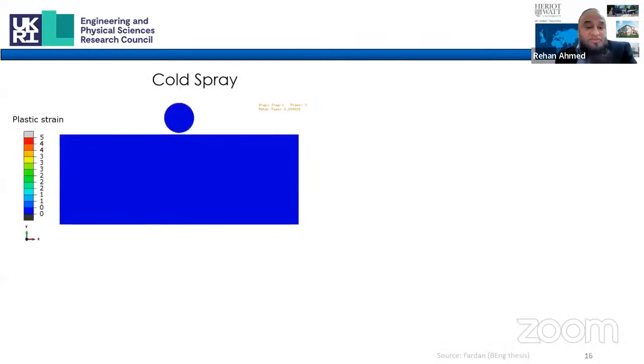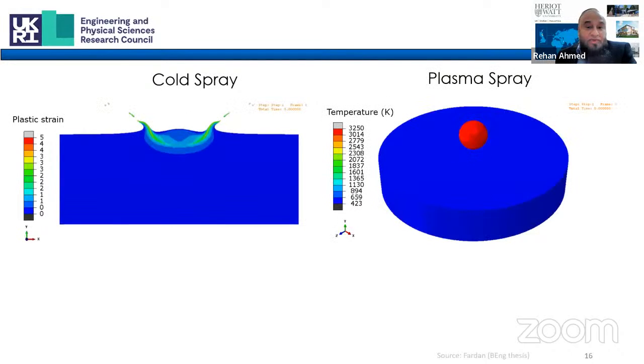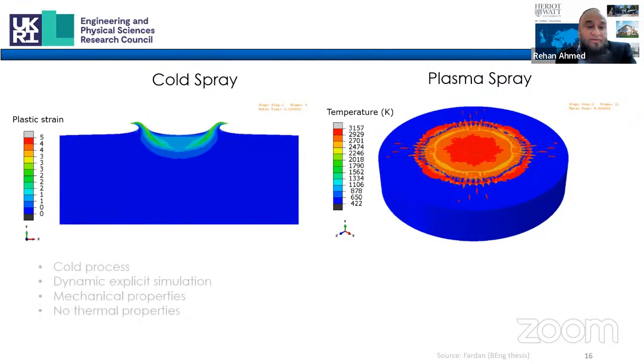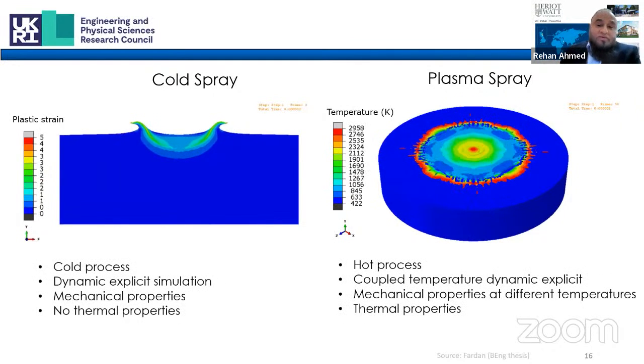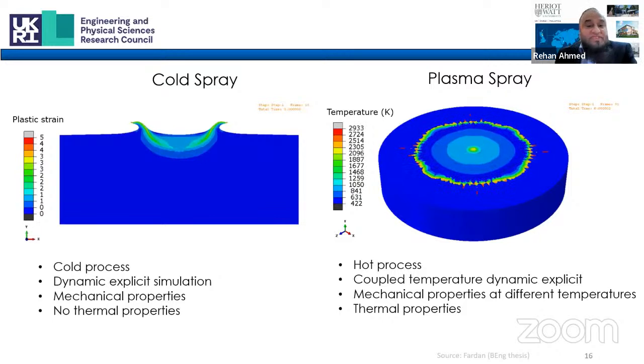And I'm just going to show 2 examples of simulations performed using the Eulerian method. On the left-hand side, cold spray is a cold process and requires only dynamic explicit simulation, and there are minimal thermal effects, and it requires mostly mechanical properties. On the right, on the other hand, plasma spray process is a hot process and material undergoes solidification. So therefore, it is crucial to include thermal properties as well as mechanical properties, which are both temperature dependent. And sometimes acquiring the right combination of properties is where the challenge lies.